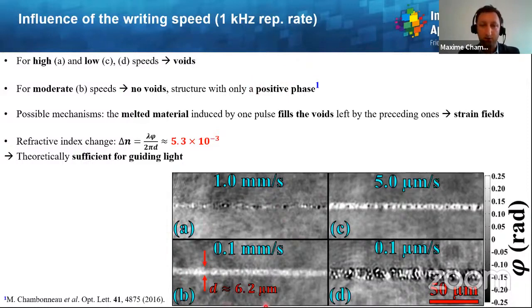In stark contrast, when the writing speed is intermediate at 0.1 millimeter per second, one can see that there is no black dot in the line, and we have inscribed the structures. We can inscribe lines with a positive phase shift, meaning that there is a positive refractive index change.